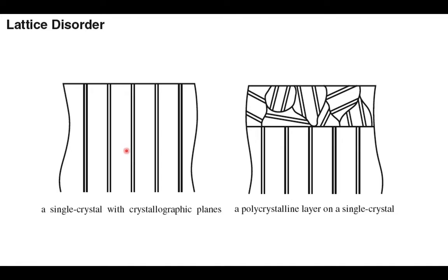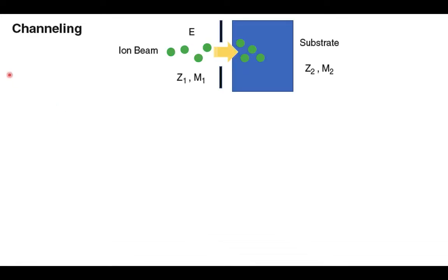So that is also another important point. To exploit that, another technique is called channeling, and channeling is also used to study the material. But you need to be careful when you use ion implantation for doping, because if you implant under channeling conditions, your distribution of the atoms will be different than in a random condition. Channeling means that when the ions penetrate, if you align the crystal to a crystallographic plane, there is some kind of channeling effect that takes place.